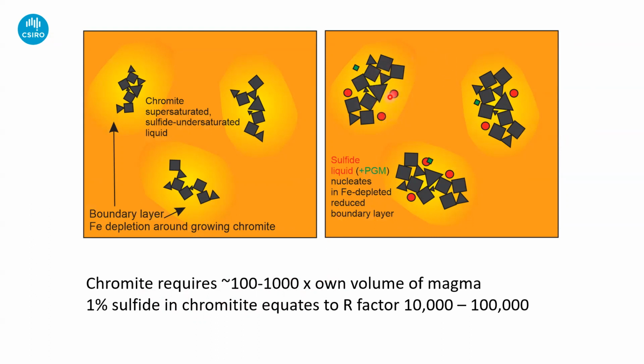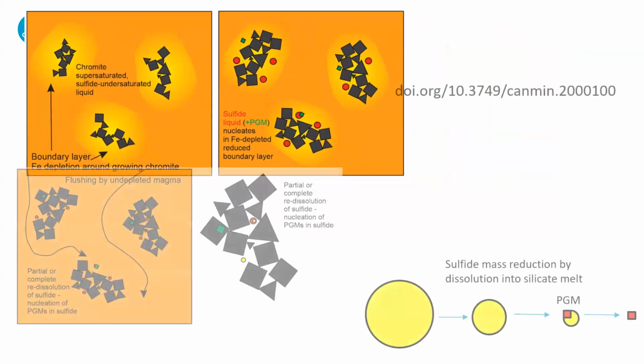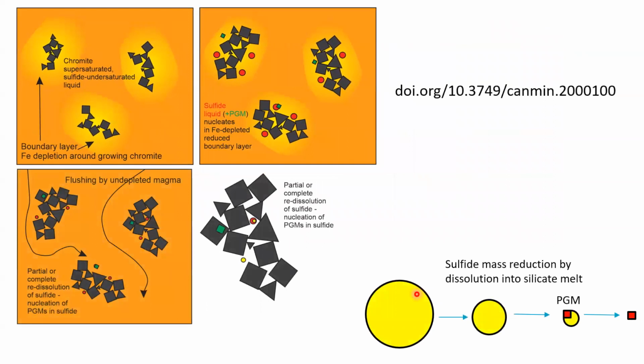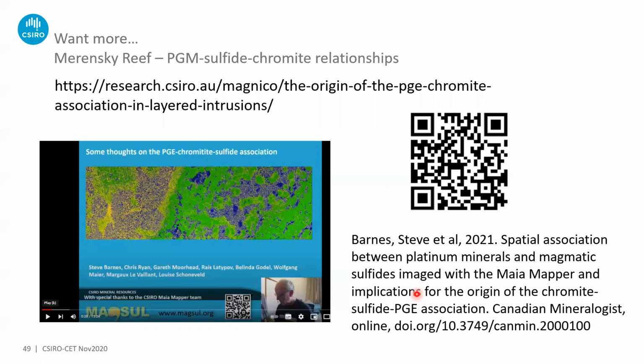So if now that chromite has got 1% sulfide in it, that 1% sulfide is now seeing 10,000 to 100,000 times its own volume of magma. In other words, it's seeing a really high R factor. That's what we need to get really high PGE concentrations into the sulfide. So we've got a few factors all working in the same direction. We're probably nucleating PGMs in this boundary layer. We're nucleating and growing sulfide at very high R factors, getting very high PGE contents. And we're then flushing this with sulfide undersaturated magma, redissolving that sulfide and leaving behind our PGMs.